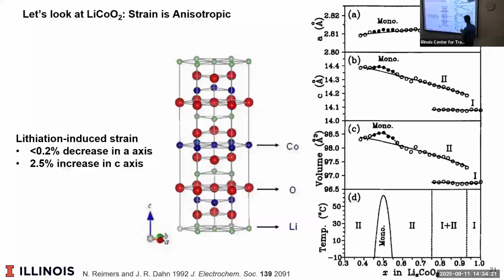If we look at the atoms here, these are the cobalt. It's just made of layers of cobalt sheets. But you can see here that the volume expands. This is charging. You start out here, and as I charge a battery, I move this way. As I'm charging my battery, it's expanding, expanding, expanding, and then it starts to contract. And one of the reasons they tell you, if you want your battery to last a long time, don't go 0 to 100, go 20 to 80, or don't keep your laptop charged at 100%. I mean, they're getting better at this. Don't lose sleep over these sorts of things with your laptop.